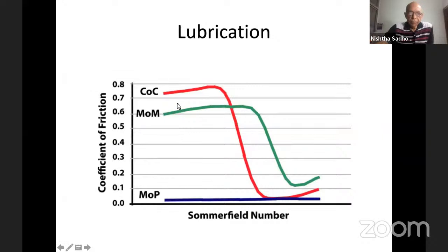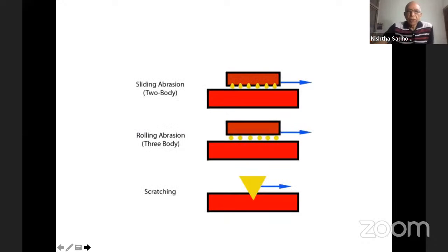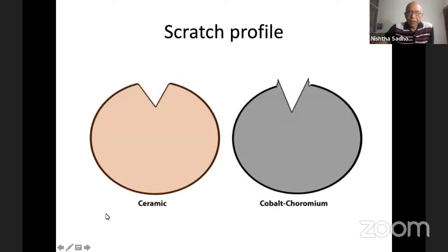The same thing happens with whatever coupling is used in the prosthesis, whether it is ceramic on ceramic, metal on metal, or metal on poly. The wear has certain different characteristics depending on the kind of friction that is produced between two surfaces. So there can be a sliding abrasion, that is one sliding over another. There can be a rolling abrasion. Third body is interposition of something hard like a cement or a bony spicule between the two surfaces. And then there is the scratching. So just as an example, a scratching on a ceramic would produce some kind of dent, whereas on a metal head like cobalt chromium, it will raise the surfaces.